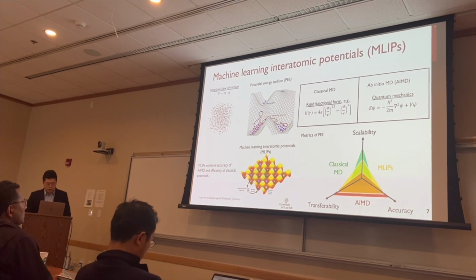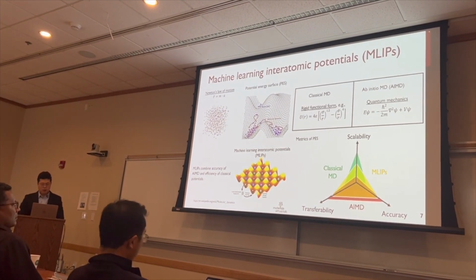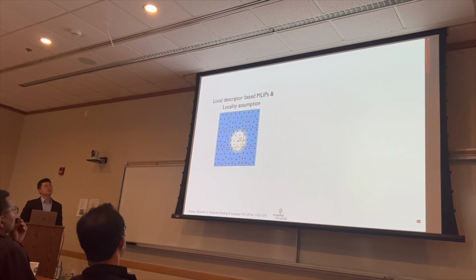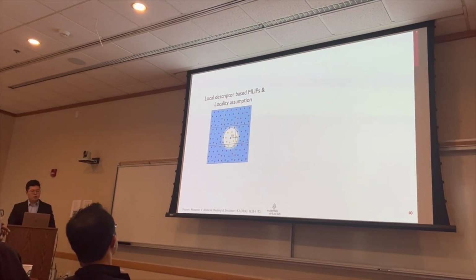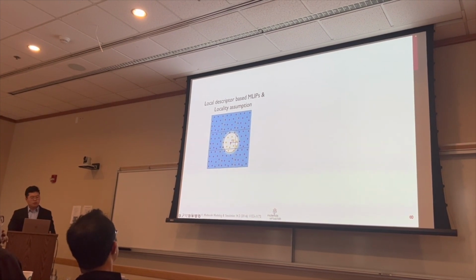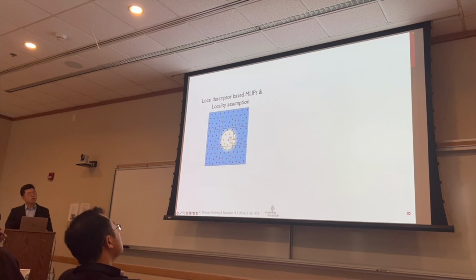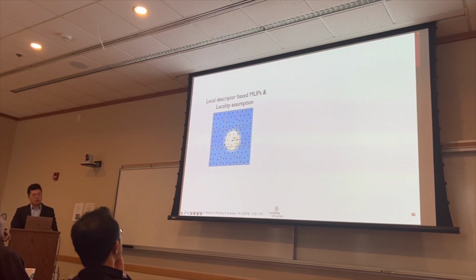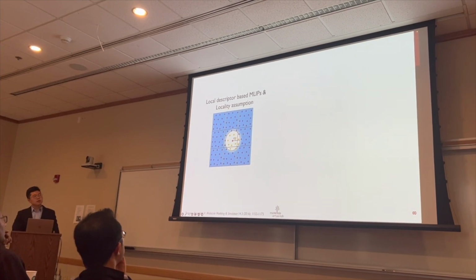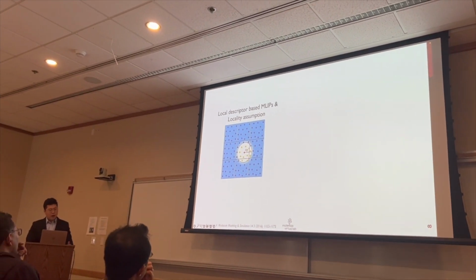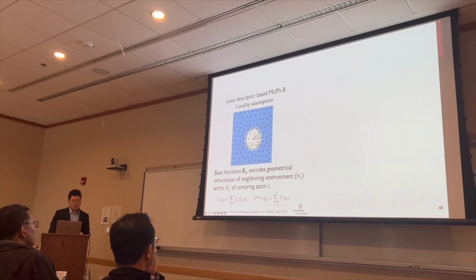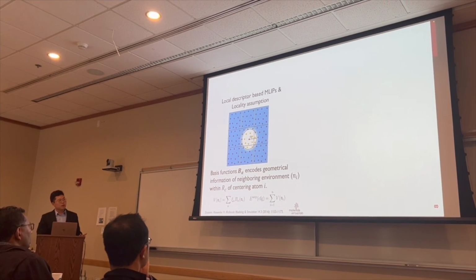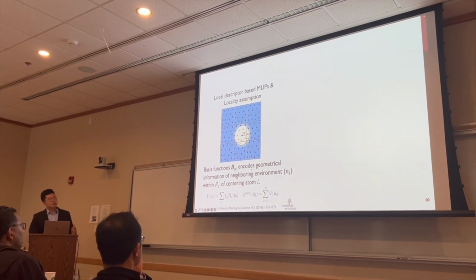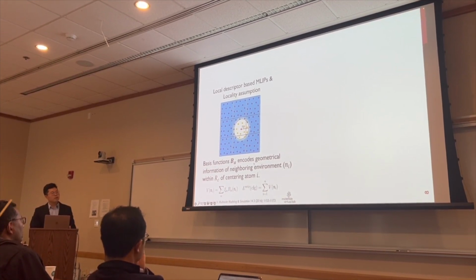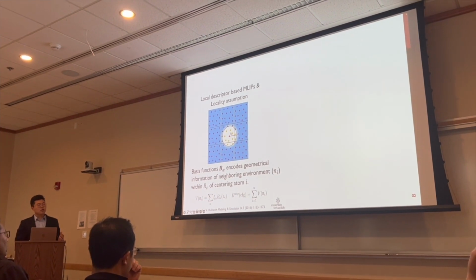So how does a machine learning interatomic potential work to achieve this great performance? When we talk about machine learning interatomic potentials, we are actually referring mostly to local descriptor-based MLIPs, which hold the locality assumption. This locality assumes that the interaction of an atom with its neighboring atoms is the most crucial, while interaction of an atom with atoms at a distance longer than a certain cutoff range can be neglected. And under this assumption, machine learning interatomic potentials define some sort of basis function, for example, here the B alpha, to encode the geometrical information of the neighboring environment surrounding each center atom.